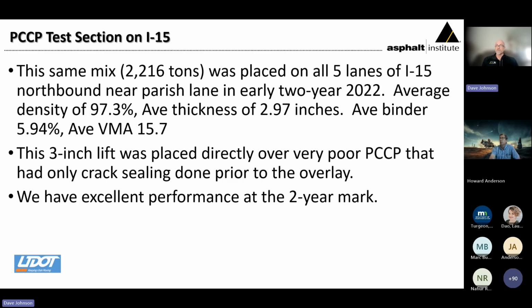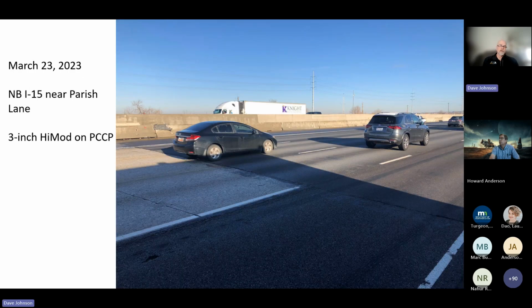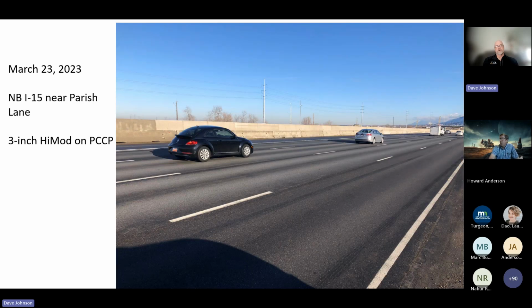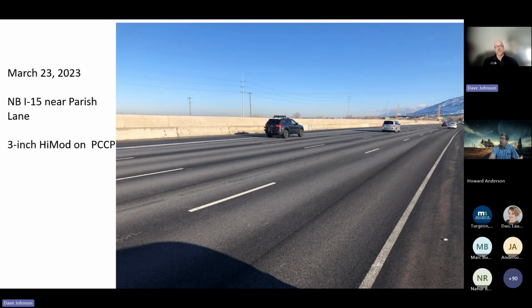I will say that from my perspective, unfortunately, they overlaid it with an SMA this past season that had been planned. But the problem with that, from my perspective, is we no longer have a visual perspective on the pavement. It was doing very well. There was no cracking to be noted, and we expect that it will continue to perform quite well. Here's some shots of that material at the beginning of that project, moving through it, and one more just for good measure. Very good performance.